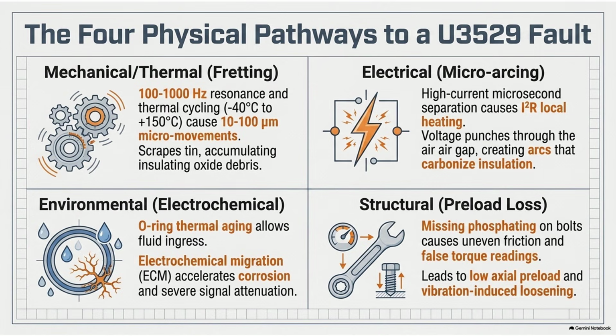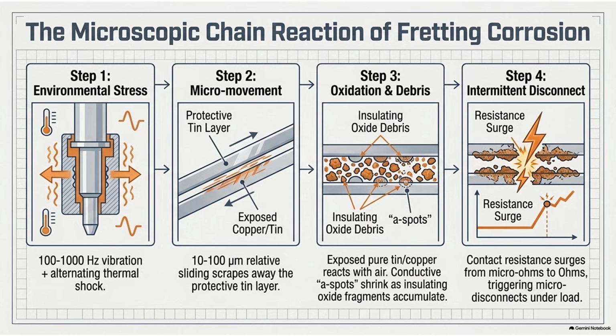A phosphating treatment acts as a microscopic dry lubricant and an anti-corrosion layer right on the threads of the bolt. It ensures that the friction between the turning bolt and the threaded hole is incredibly smooth and uniform. Got it. If that chemical treatment is missing, or even just unevenly applied, the raw steel surface of the threads is rough. So the robotic screwdriver starts driving this untreated rough bolt into the hole? Yes, and as it turns, it hits a patch of high friction on the raw metal threads.